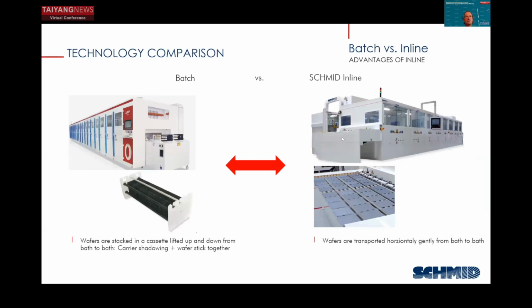Very important for us, as I explained in my introduction, is that we early on replaced batch systems, which are currently dominating, but we are really on the quest and convinced that the inline solution is, for several reasons, a superior solution. The wafers run gently through the system, as you can see on the transport layer here, from bath to bath, versus stacking the wafers into a cassette that is moved around.